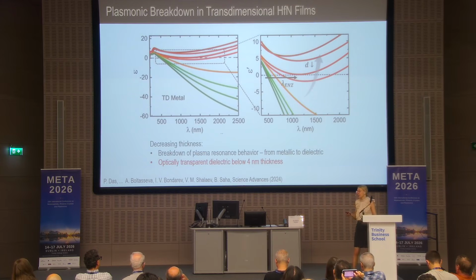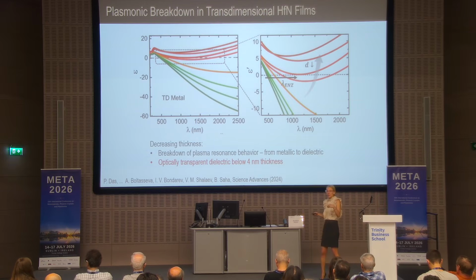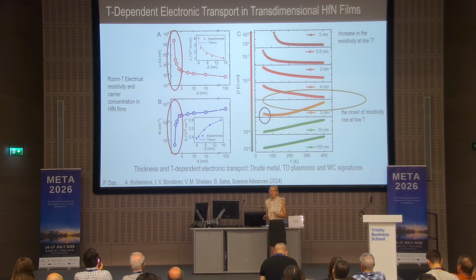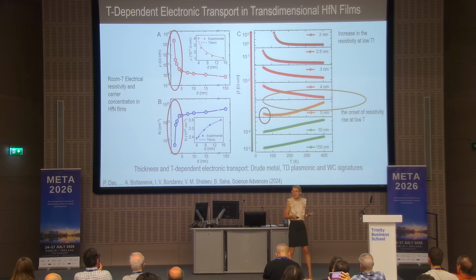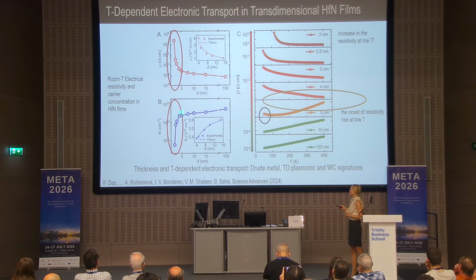So in hafnium nitride, when we go from thin films that show conventional metallic behavior to something below 4 nanometers, you see that the material goes through this metal to insulator transition. It becomes totally transparent. So this is an optical feature. But the most important and interesting features are observed in resistivity and carrier concentration. The carrier concentration goes abruptly down for thicknesses below 4 nanometers. Resistivity rises.